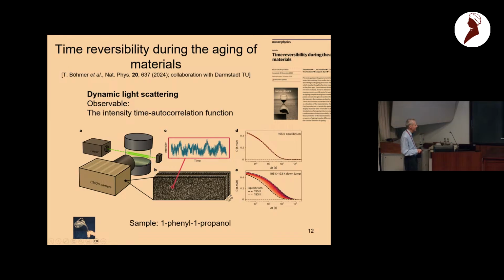And then the individual pixels will have an intensity which looks like this, and you can then work out the ensemble average time autocorrelation function. So this is how it looks in equilibrium, and this is a jump from a high temperature and 2 Kelvin down. So we start here, and we end up here.